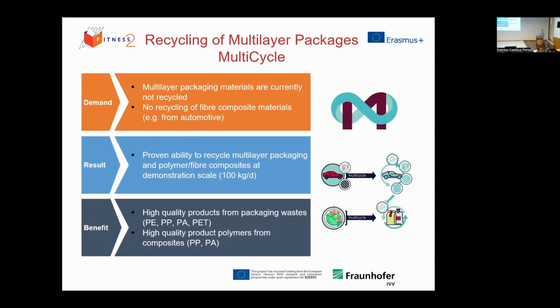And now I come to another project funded by the EU called Multicycle. Here we've also proven that multilayers are recyclable with the CreaSolv process, next to the recycling of fiber composite materials, which were also part of this project, but I want to focus on the recycling of the multilayers. And we've demonstrated this on a scale of 100 kilograms per day, and we have obtained high quality products from packaging wastes. So we have obtained pure PE, PP, PA and PET fractions with a solvent-based recycling.